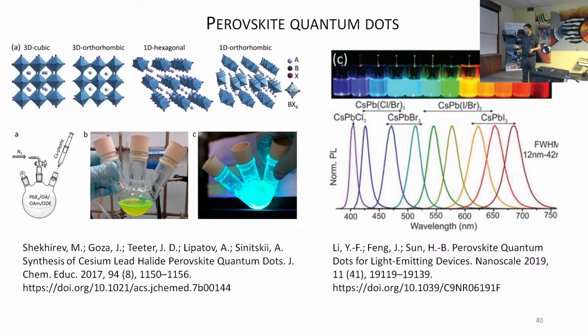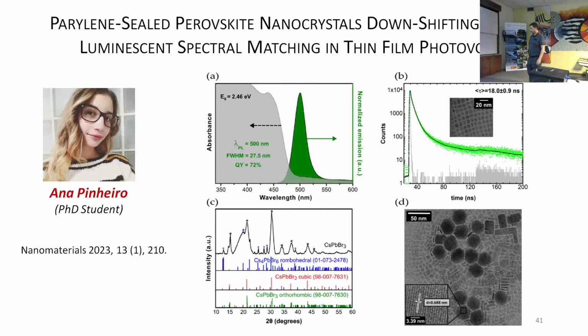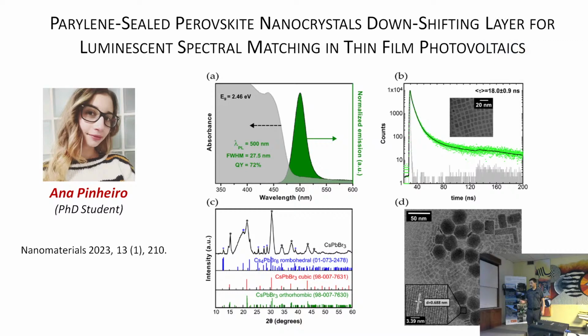But anyway, if you change the composition of this quantum dot, you can go with emission from the violet till the red. So you can cover a big spectral range with this type of materials. Then Ana Pinheiro, which today is not here, but she will be here next Monday, synthesized these quantum dots, the poor girl, and after a big struggle, she managed to produce these ones with green fluorescence and with a very acceptable fluorescence quantum yield of about 72%. This is the luminescence decay, which is highly non-exponential because we have a mix of types of quantum dots and crystalline structures that we could investigate by then. It doesn't matter anyway because we are trying to produce a luminescent solar concentrator and not a very well-defined quantum dot.